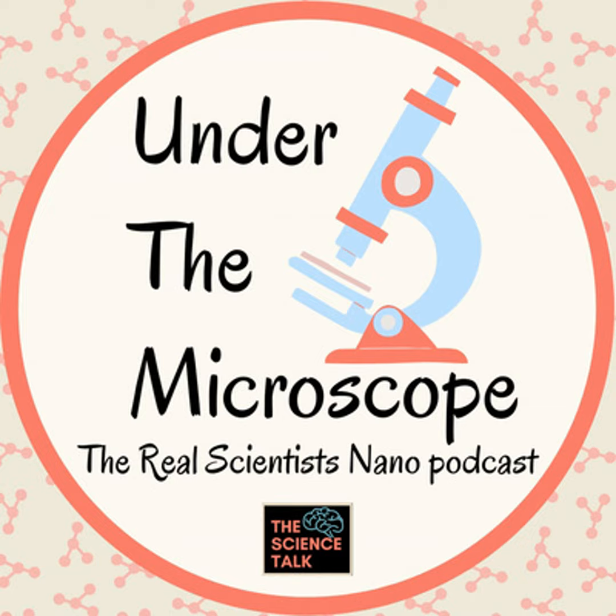Oh, wow. Yeah. And that was, to me, a complete surprise. Maybe because I'm an experimentalist at heart, so I didn't think hard about what I was going to get. It was very common to think that the wires grow as hexagons, depending on the crystal structure, whether they're wurtzite or zinc blende, depending on the growth conditions that you use. But in this case, there was some energy compromise between the facets that they want to grow and the facets that it's convenient for them to grow because of the confinement induced by the stripe.